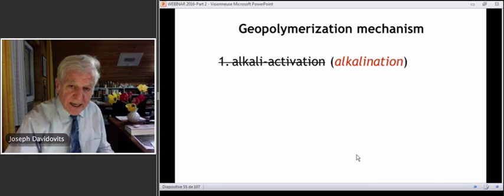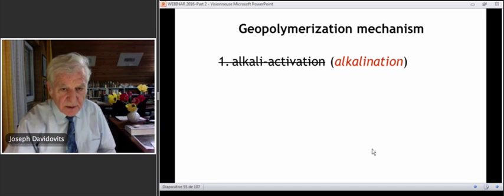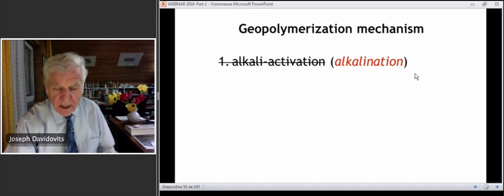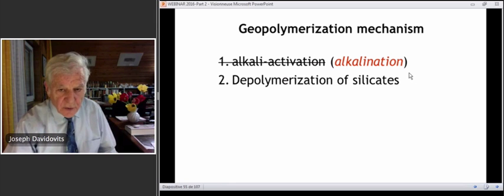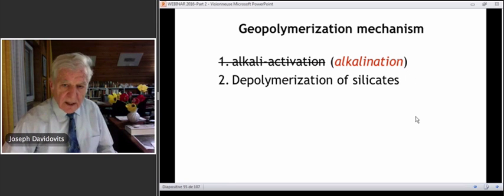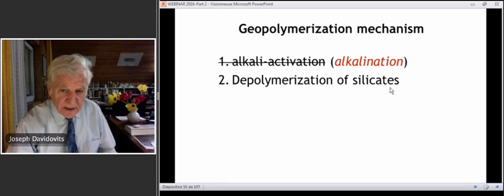The geopolymerization mechanism follows these steps. First we have alkalination. We introduce alkali, we have an alkaline medium. We don't have to activate anything. Then through this alkali medium, we are depolymerizing the silicates. Silicates are big molecules and they are cut into smaller molecules, depolymerized.